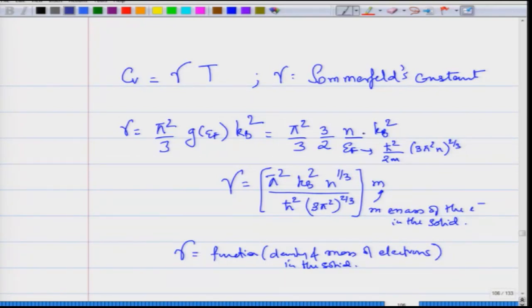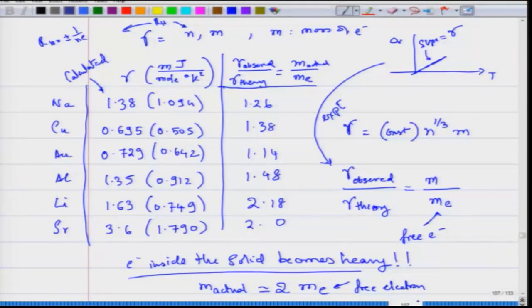And if you put in the value of the density of states, and the Fermi energy, which is related to the mass of the electron, you can show that this constant is directly proportional to the mass of the electron inside the solid. So if you measure the specific heat of the electron gas as a function of temperature, from the slope of Cv versus T of the electron gas, you can determine gamma. That is what people did in experiments at very low temperatures. They measured the specific heat as a function of temperature, and from the slope, you can measure gamma, which is proportional to the mass.